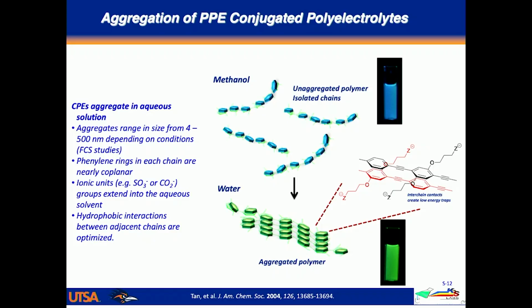So this was a fundamental effect. I should mention that we have quite a bit of evidence for the existence of these aggregate structures using light scattering methods as well as fluorescent scattering methods. And in addition, it's very likely that this aggregation is driven by a hydrophobic effect. It's much like the formation of soap micelles that occurs when you put soap molecules into water.